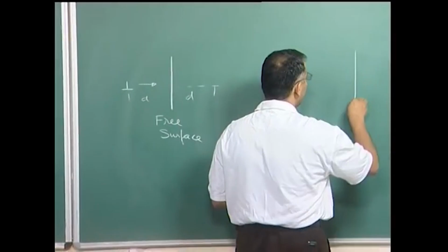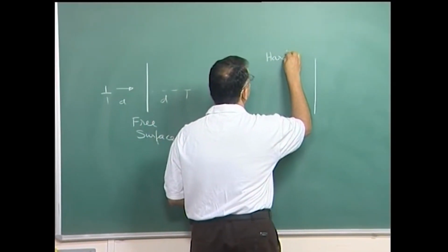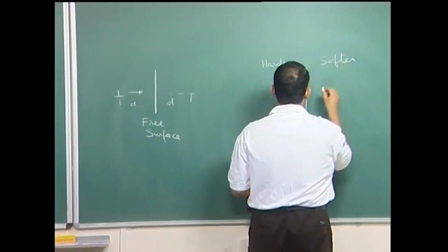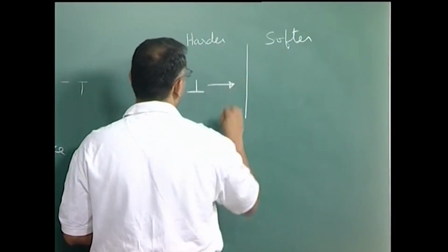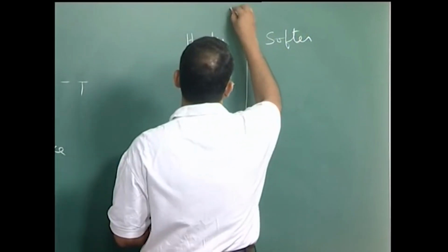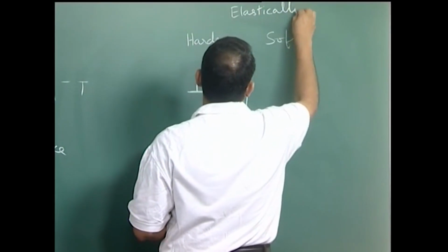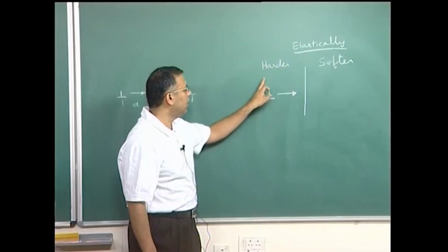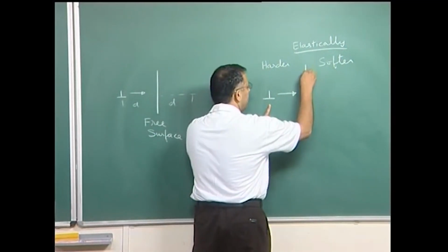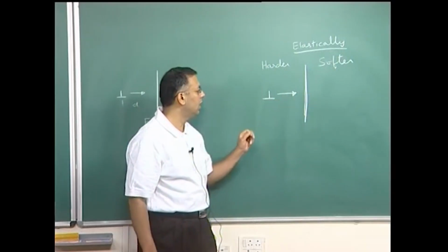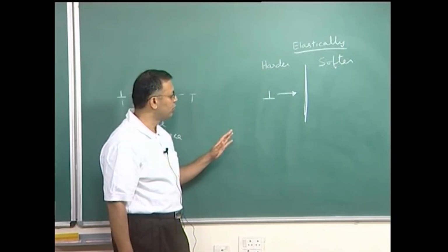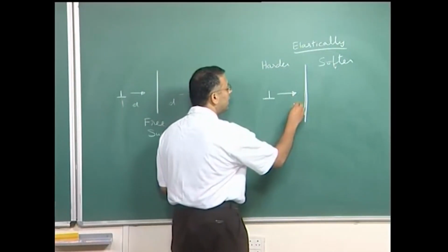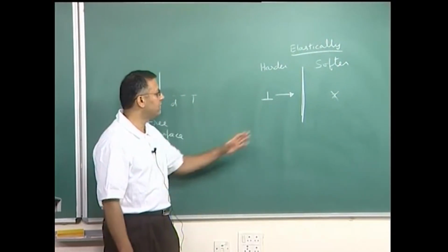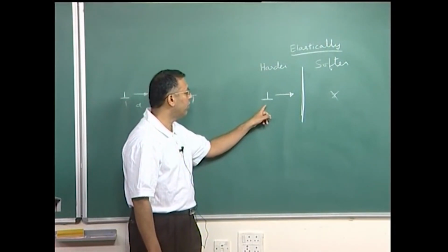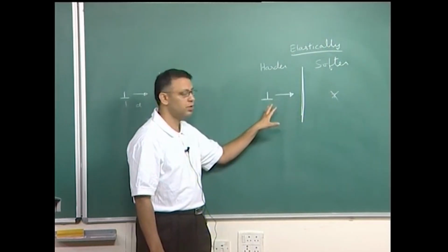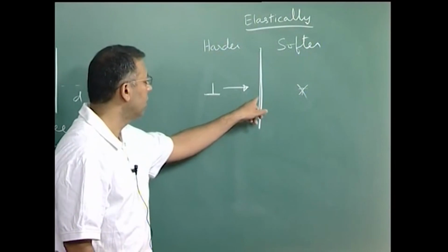And such a configurational force can also exist between, for instance, a harder material and a softer material. And if I put a dislocation in a harder material, it will be attracted towards the softer material, and I am talking about elastically harder or softer. So, if I have a harder material and the dislocation sits in the harder material and there is an interface with a softer material, then the dislocation may feel a force towards the softer material, and this kind of configurational force can of course loosely be called an image force, even though we should understand that actually now I cannot have an image construction, because this is not valid anymore, this is not a free surface, this is a softer material. Nevertheless, the dislocation will feel a configurational force towards a softer interface, because now the energy of the system would tend to decrease as the dislocation is positioned closer and closer to the softer material.